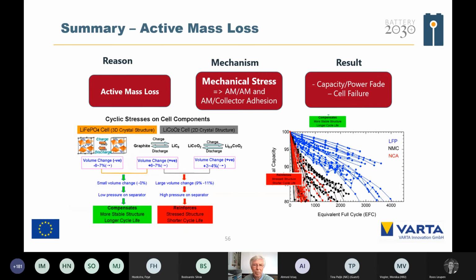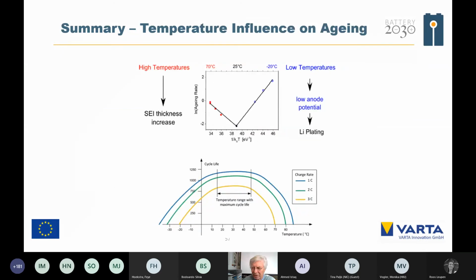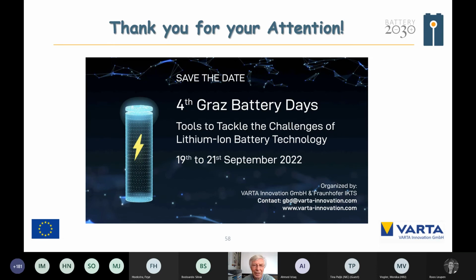And for active mass losses, we have mechanical stresses in 2 different systems, as you could see here. Systems with low stress, like LFP, have a longer lifetime in relation to systems with higher stress, and those are the layered materials like NMC and NCA. And in the summary of the temperature influence, you could see here, it is not as we expected. Low temperature could be very good for the aging? No, this is not the case, caused by lithium plating. So again, thank you very much for your attention, and also see the Graz Battery Days in September.